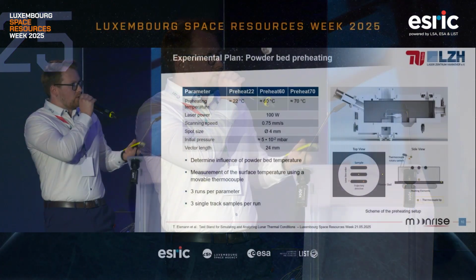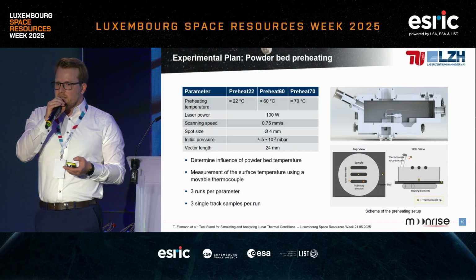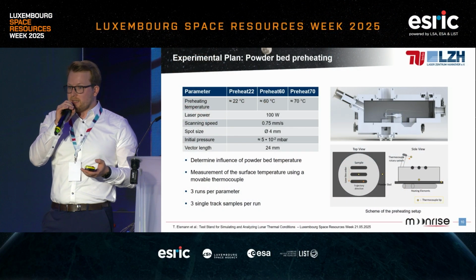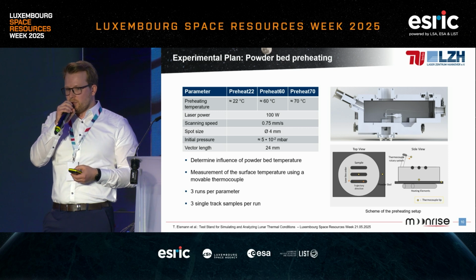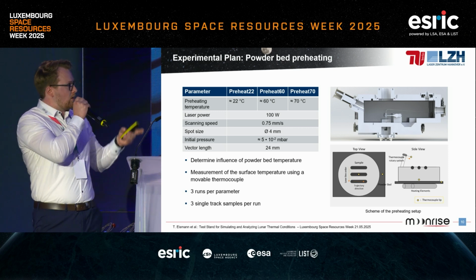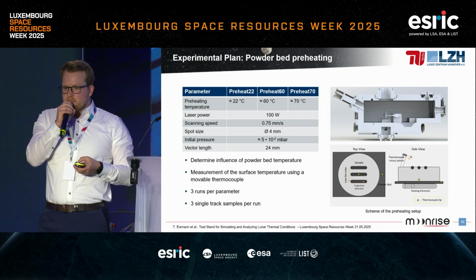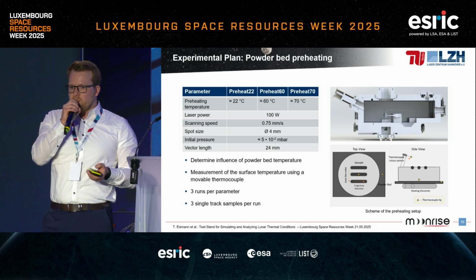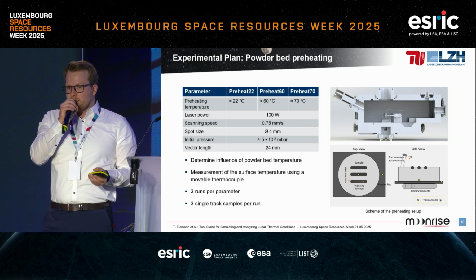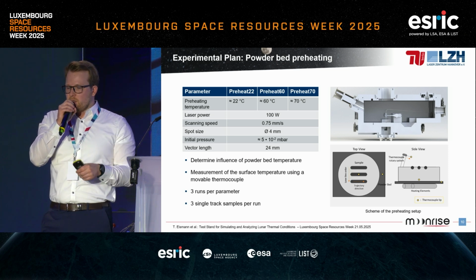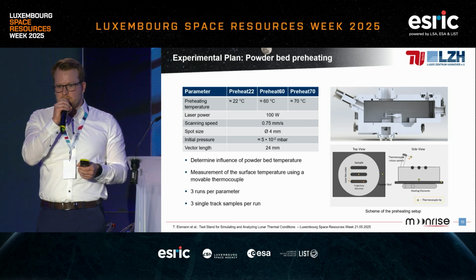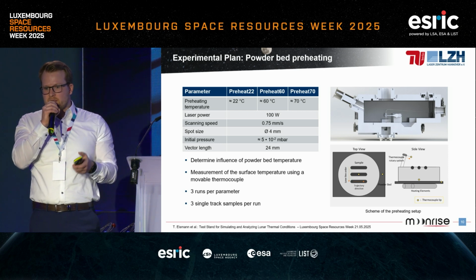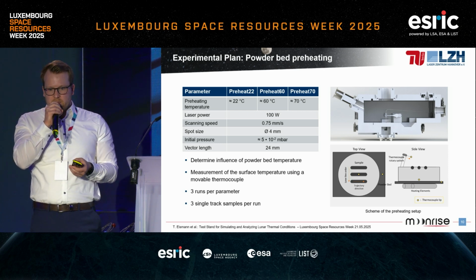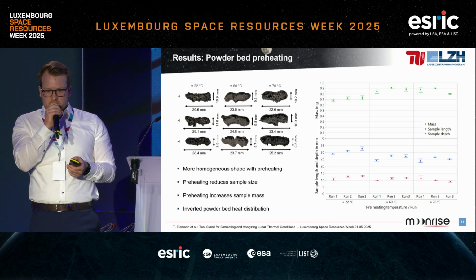Therefore, we used the heating elements to preheat the powder bed from the bottom to the top in order to test if an elevated powder bed temperature, like it might happen on the moon, influences the process. There you can see our process parameters, and it's important to say that we had a movable thermocouple that is going on the top of the powder bed surface in order to measure the temperature there. In that case, we did only single track samples. And the results show us the following.